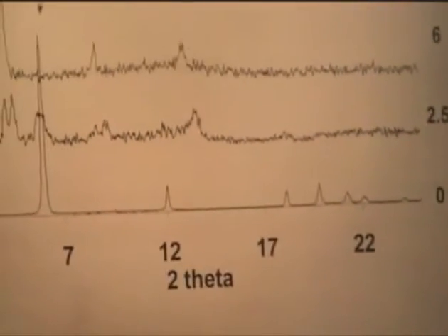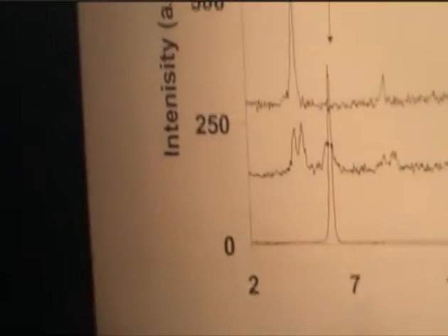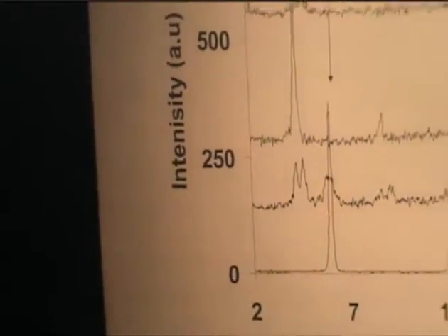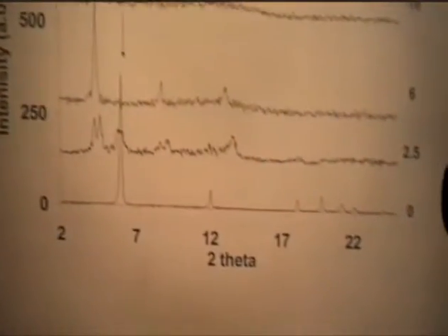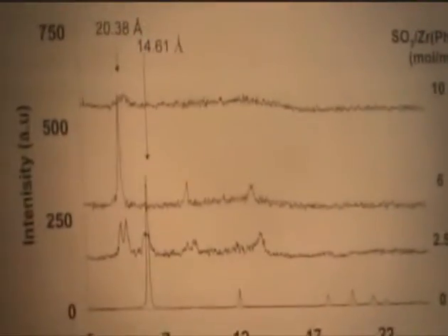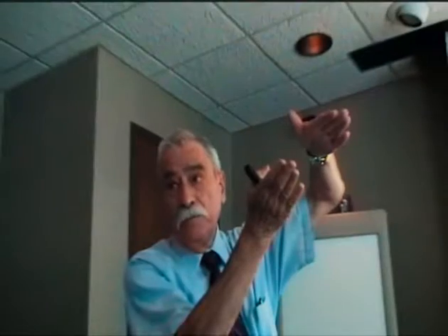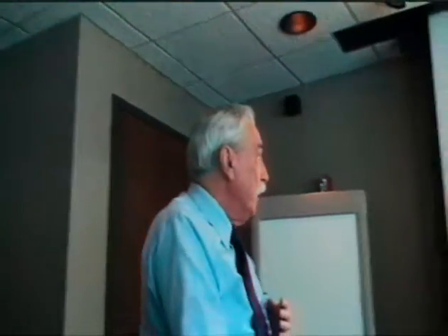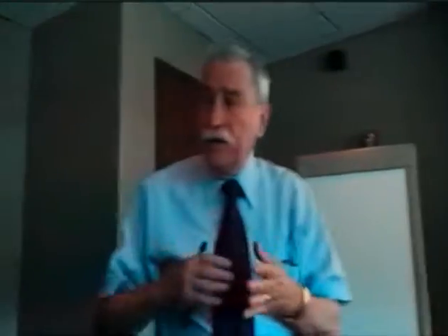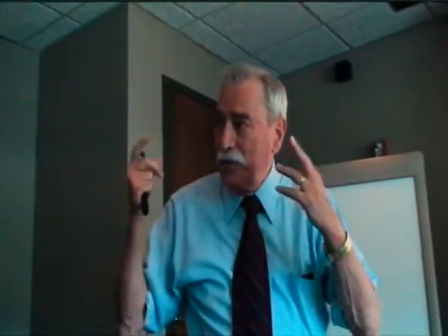This is the phenylphosphonate, which we did work the structure out, okay? So you have the two phenyl groups pointing at each other like that. So it's 14.8 angstroms, I think, in the interlayer distance. When we cross-link them, it's about 13.8 because now you've reduced it because you have no van der Waals space in between the rings. And you see, they don't exfoliate because you've cross-linked them all the way along the line. The particles are very stable.